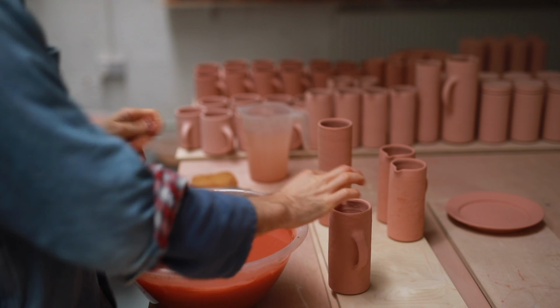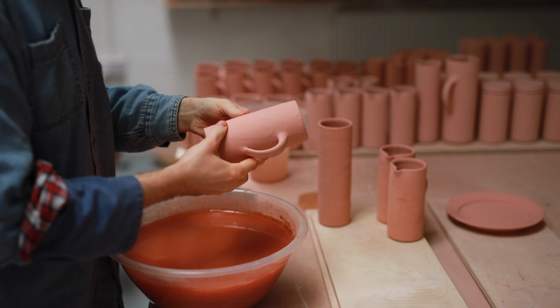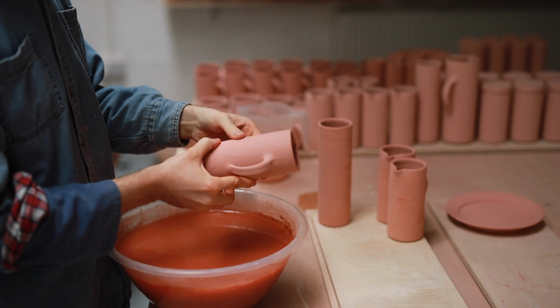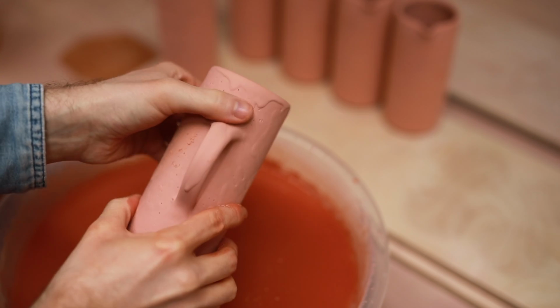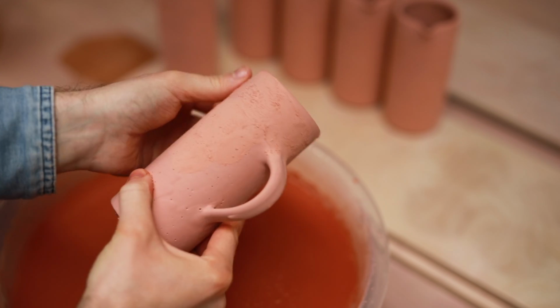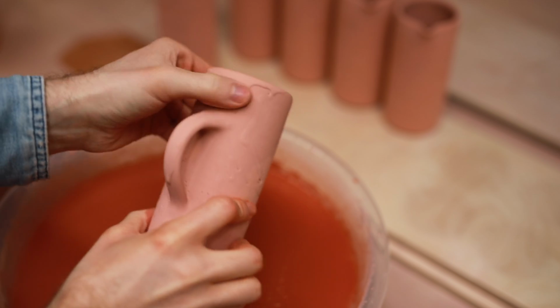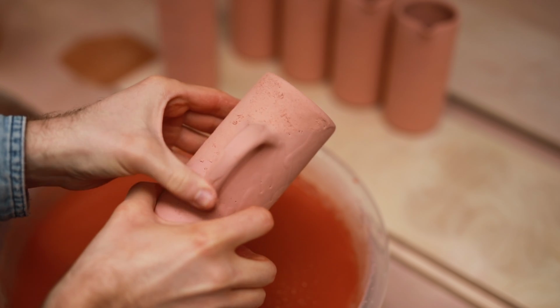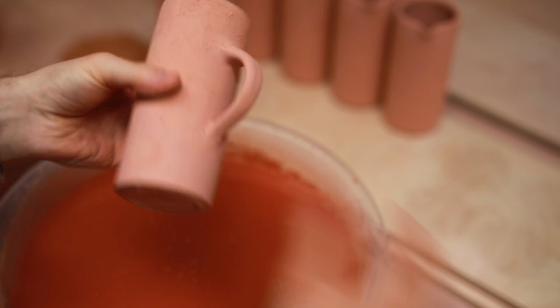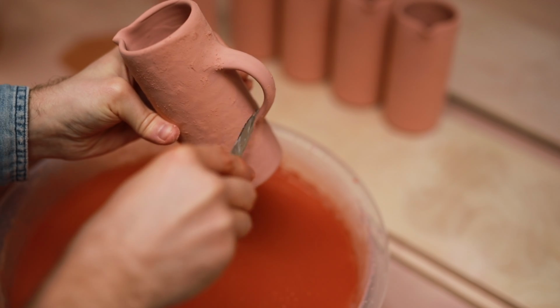Once glazed, I'll leave the pots for a number of days. This way the moisture in the clay body evaporates and the powder becomes a lot easier to clean up. I simply rub over any excess drip marks and the tong marks, and generally I just try to make the glaze surface as smooth and even as possible, as the neater it is now, the neater it'll look once fired.